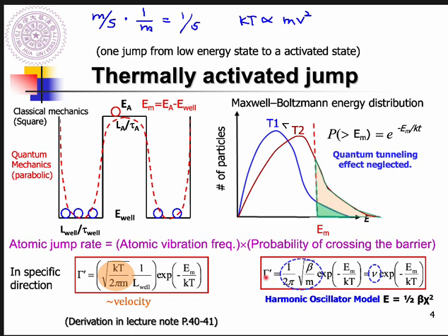So now you know that the jump rate, gamma prime, in specific directions will be affected by beta, the force constant, spring constant, or bond strength, and the reduced mass for the atoms, and also the migration energy, and also the working, I mean environment, temperature.